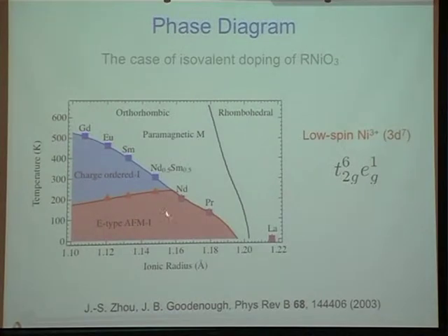Okay, so let me start with this case of strained nickelate films. Andy already showed this phase diagram. So nickelates, nominally from an ionic point of view, are a d7 system. So they have a fully occupied t2g orbital with one eg electron. Although they're not Jahn-Teller active, which you would expect with one eg electron, and that's a whole talk in itself, which I won't go into. But it's the reason that these materials were interesting, because they have one electron in that eg orbital. So if you can really split those orbitals, it's a good system for this.